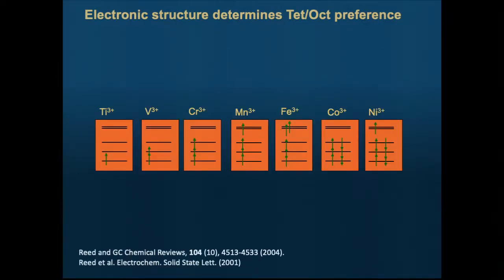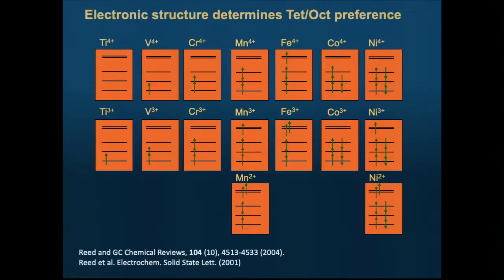So let's go through the periodic table now. Basically we have 3+ or 4+ ions: 3+ in the discharge state, 4+ in the charge state. So I'll put the 4+, the 3+, and in some cases the 2+ are relevant as well. Like you take titanium 3+. This is not going to be a good ion because it has only 1 electron in its stabilizing energy level. So titanium will migrate, and that's exactly what it does. So does vanadium and chromium. Chromium looks great because, spin polarized, it has 3 electrons, but when you oxidize it, there's only 2 left, and you don't have enough stabilization to keep it in the octahedral site. So basically, these 2 are out, this one is out.